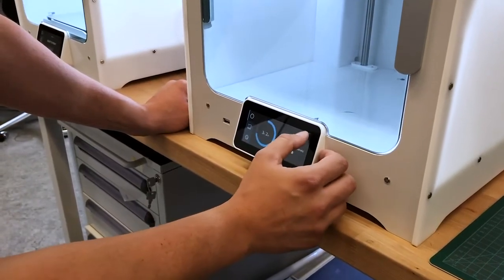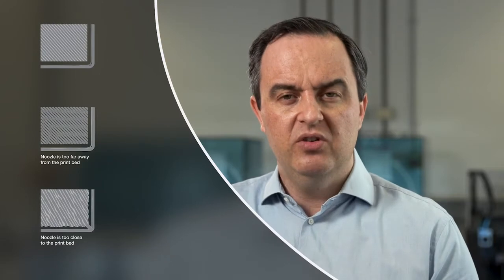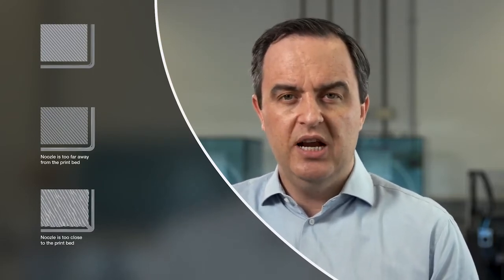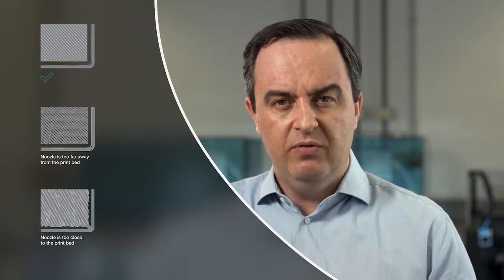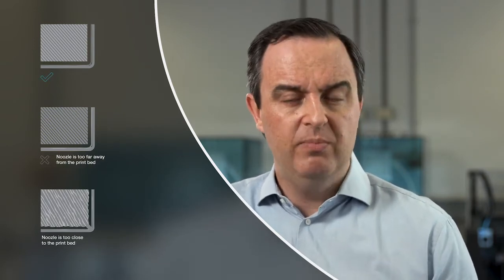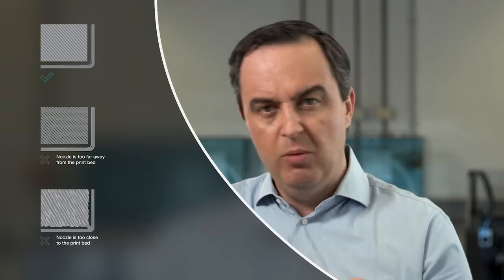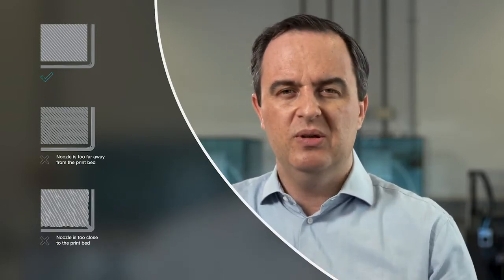Sometimes when your extrusion is tuned high enough to produce dense parts, you will get a certain amount of buildup at the nozzle surface, and that's typically normal for us. We want to have enough material that's ensuring full density. At the same time, sometimes people will look at it and think it's kind of strange. Now, of course, like any good thing, too much is a problem. Those parts can crumble off the nozzle and block other things, so it's something to be balanced.